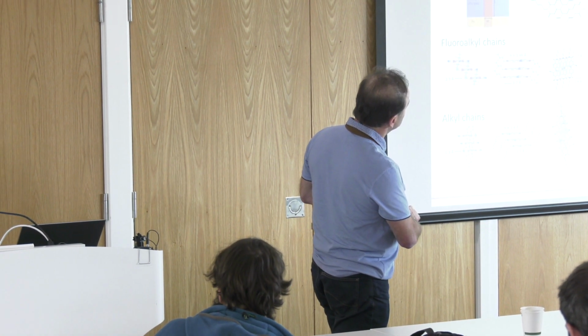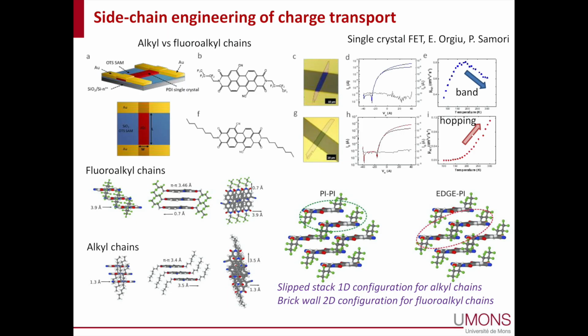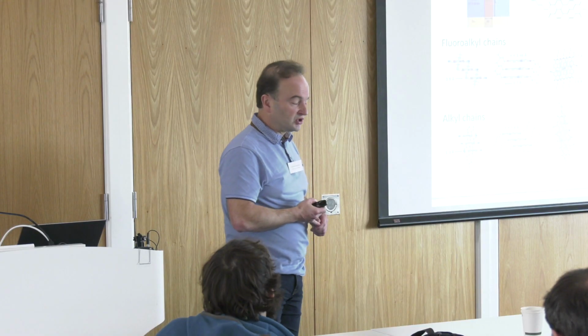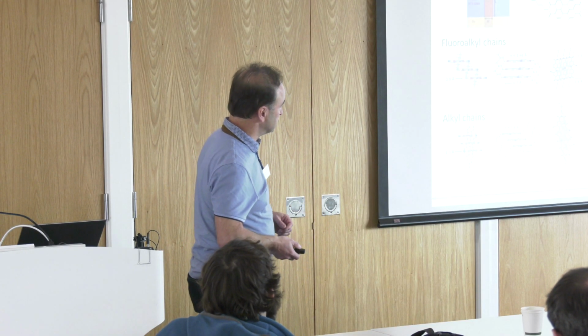And if you extract the mobility versus temperature from the transfer curves of the field effect transistor, you end up with something that increases steadily with temperature for that molecule, but that shows, at least in this temperature window, a band-like behavior where the mobility decreases when you increase the temperature. So this is a subtle change in the chemical structure that leads to apparently very different behavior in terms of the charge carrier mobility, which we wanted to understand.